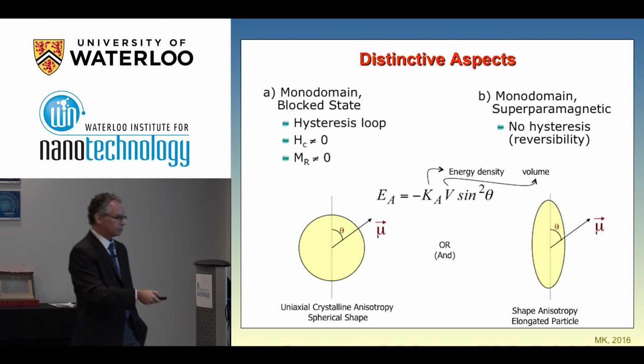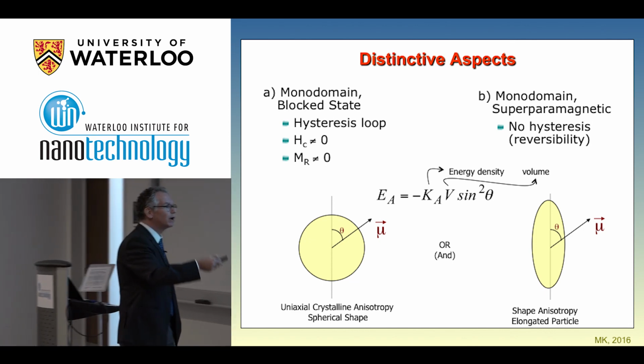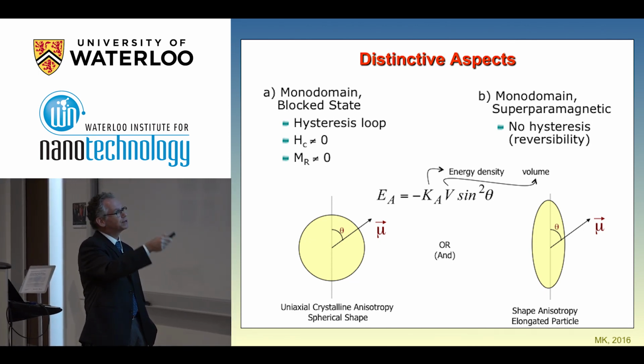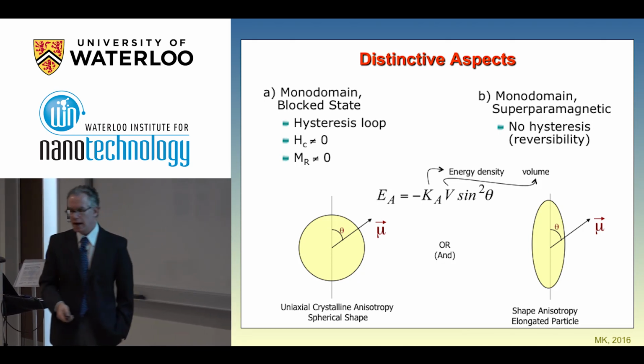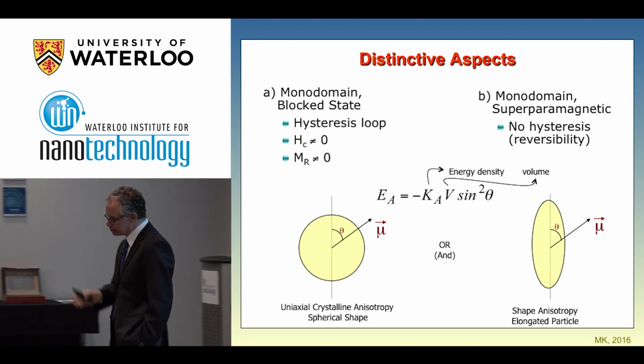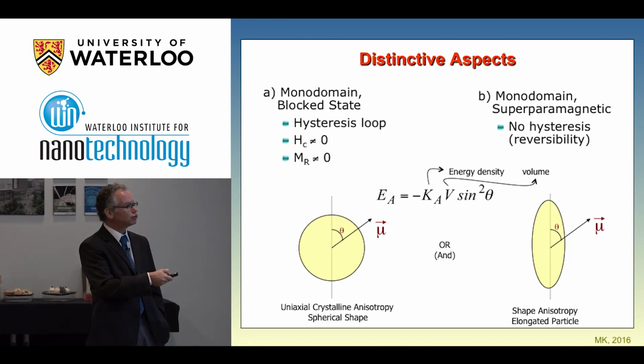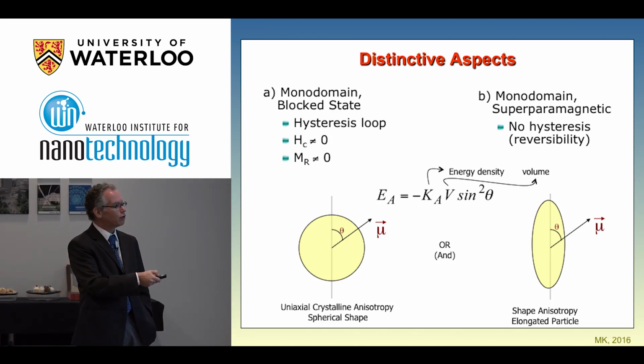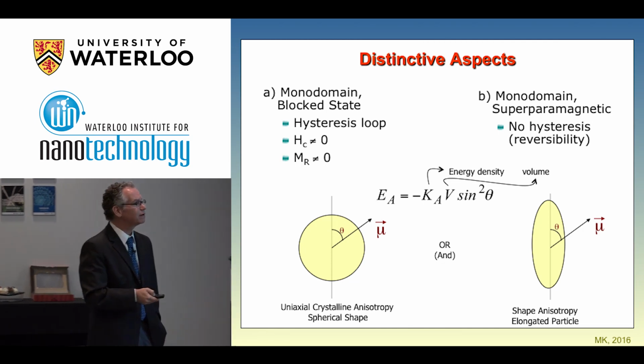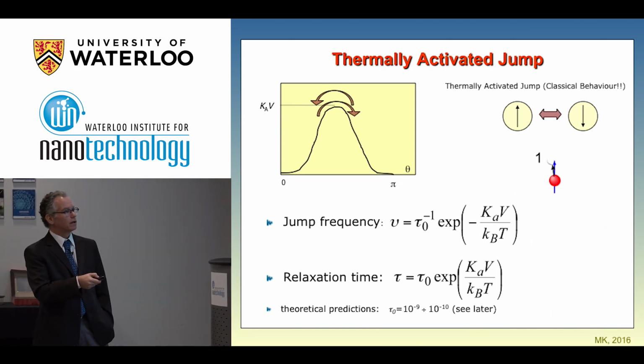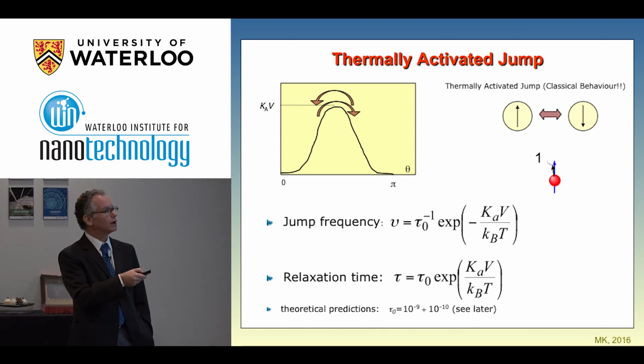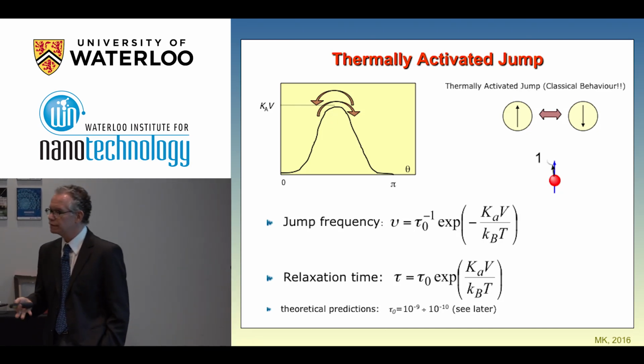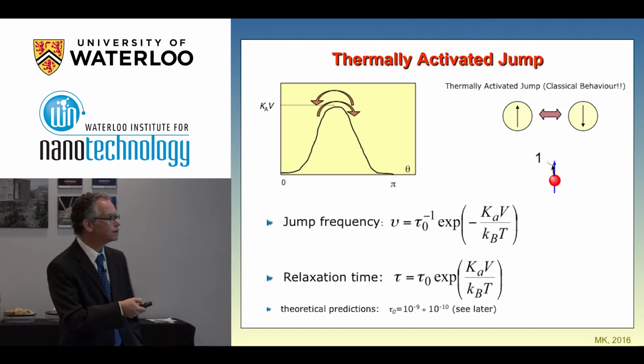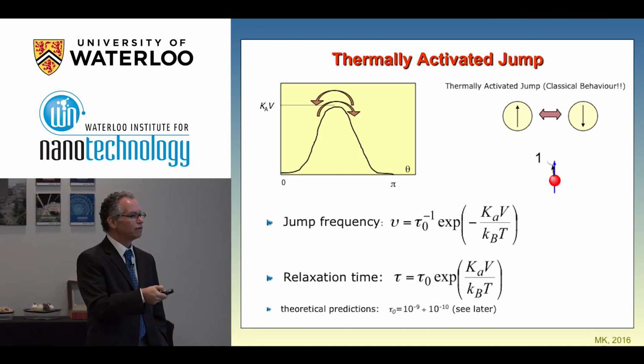So you have one particle or one region of a magnetic material which has anisotropy, so it prefers a specific direction for the magnetization to lie, and then you can jump from one to another with this energy landscape, as I mentioned before. So you can have this kind of picture. You can go from 0 to 1, and then you can make a rather common statistical treatment to solve this problem. So this is an Arrhenius frequency jump.